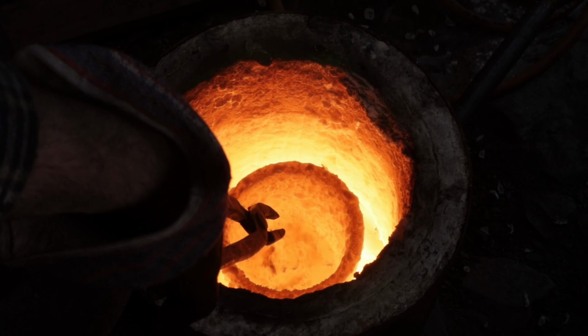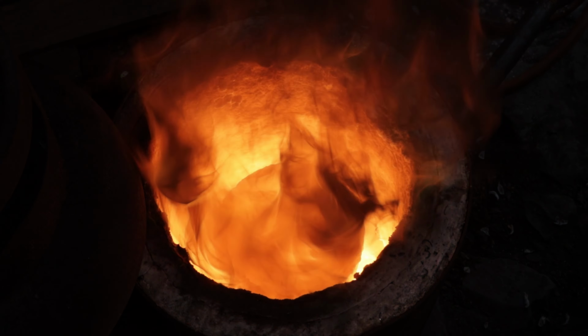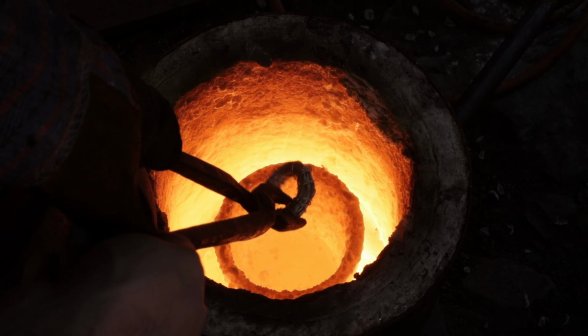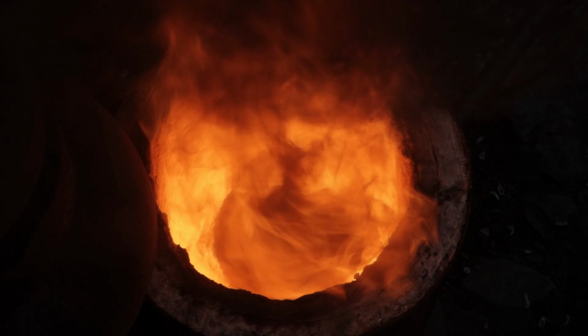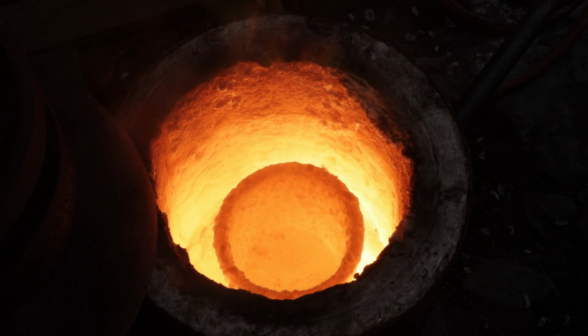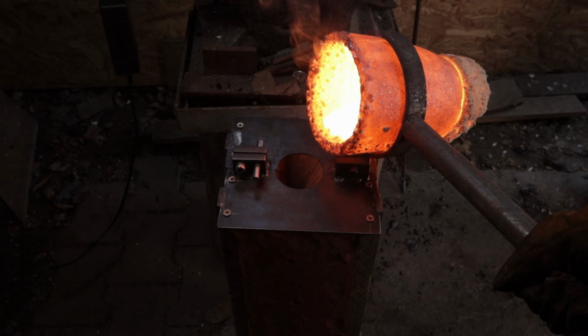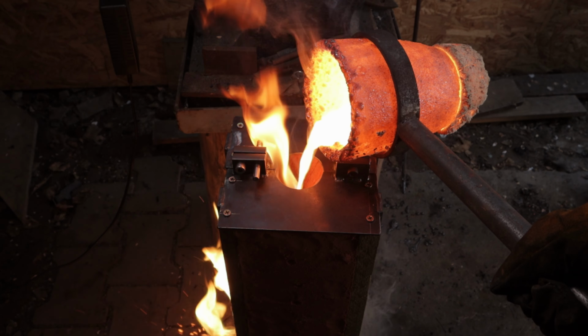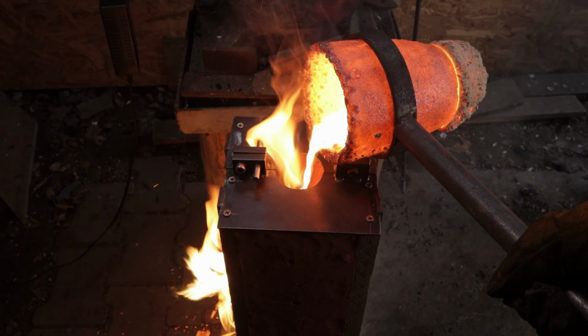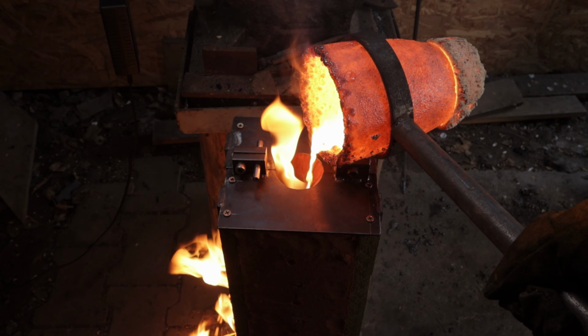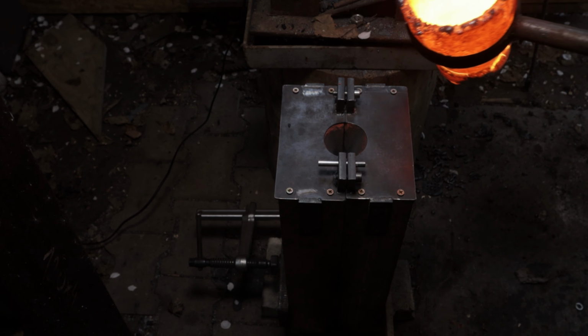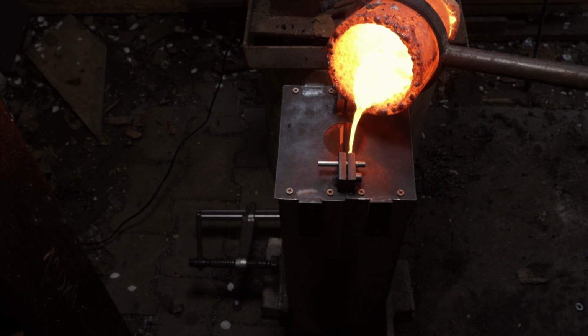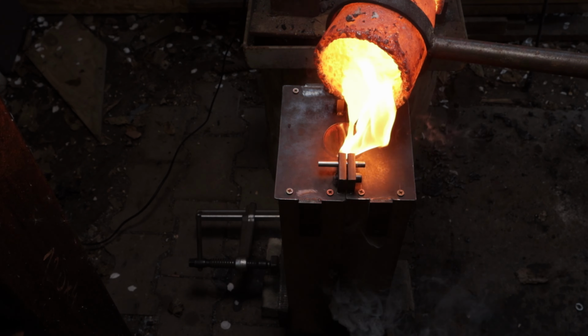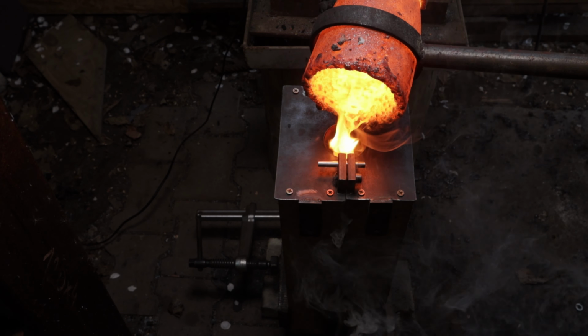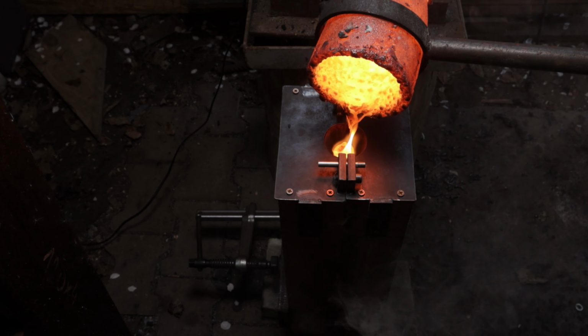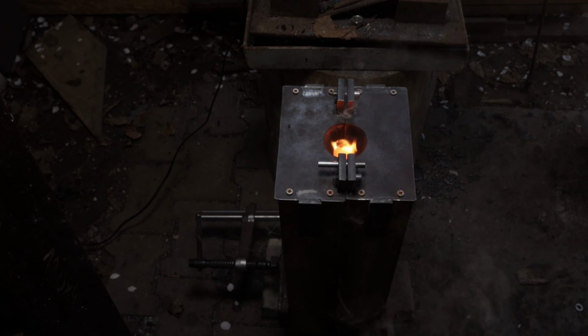This is the very moment I turned copper into bronze, by adding the tin into the molten metal. This is my first vertical pour, and what can I say? I underestimated the mold construction and overestimated the size of the vent channels. I reinforced the seam of the mold by adding a strong clamp, and the result is way better this time.